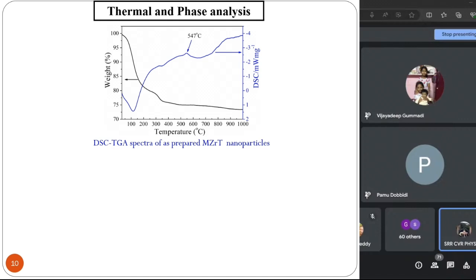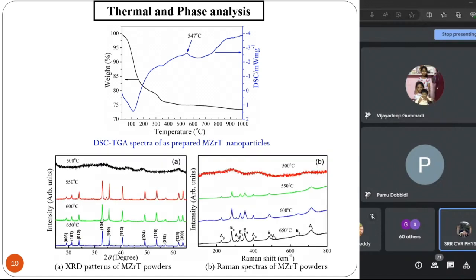Can you enter? Yeah. So when you do that, you see that we have calcined the material at different temperatures. Based on the above, when we calcined at 500 degrees C, there is no phase formation. When we see 550, there is a phase formation. When we do 600, we get a good phase formation. Even 650, good phase formation.